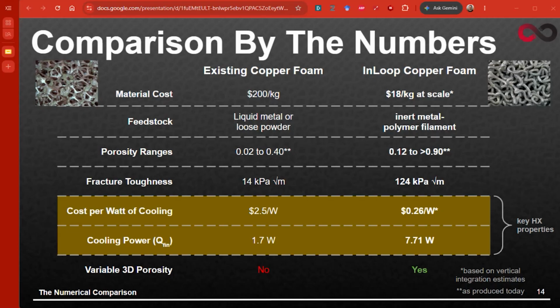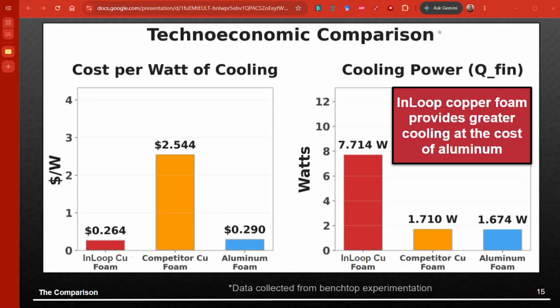We set up a couple heat exchanger experiments with different metal foams, stuff on the market today, as well as our copper metal foam. And we found that we could produce a heat exchanger with a better cost per watt of cooling because it was able to remove so much heat from a PC, a hot plate, basically. And we can also provide variable 3D porosity, which is critical for certain applications in thermal and mechanical work. Some of the numbers from an experiment are presented in these very simple charts here, just to give you a sense of how we compare to the competitors.